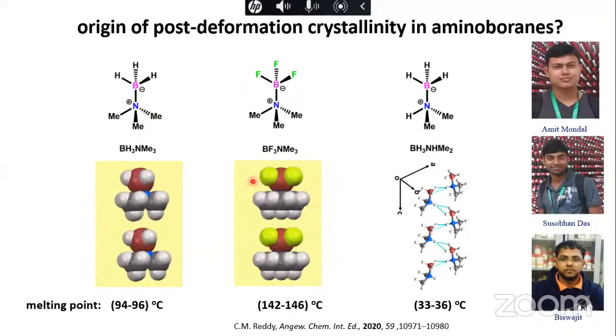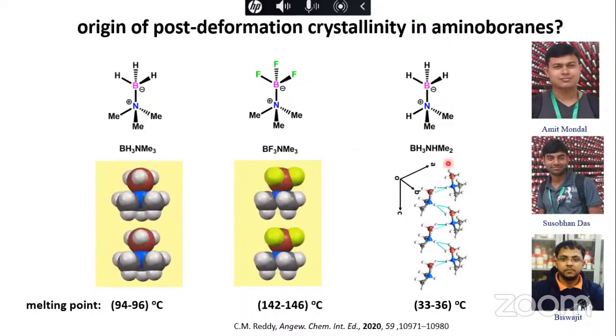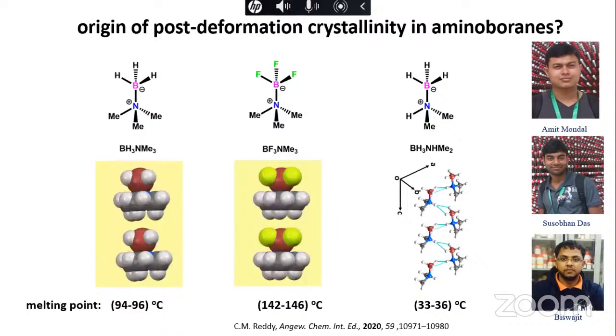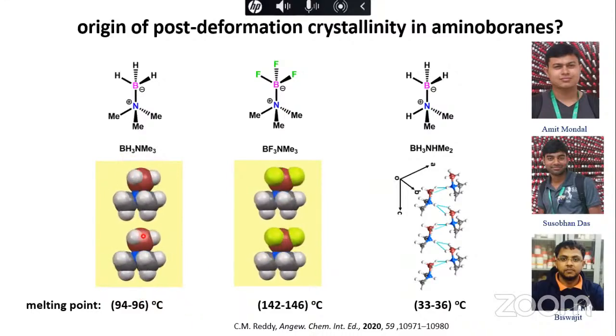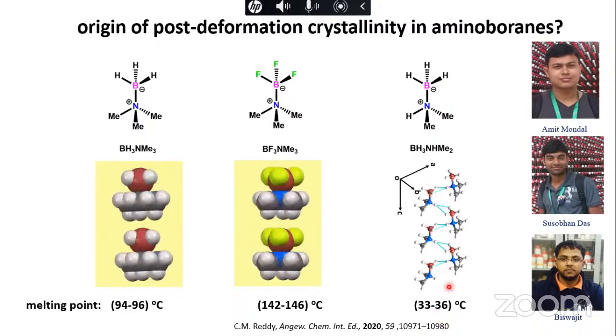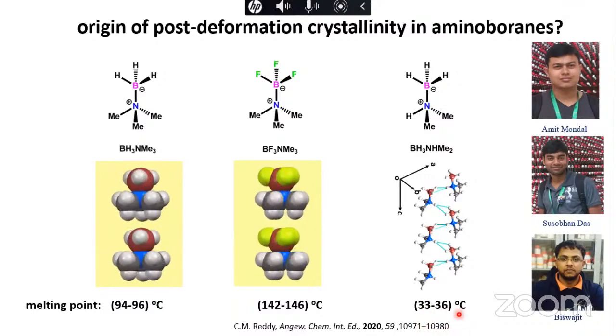And that is why these form these dynamic crystals where you have rotational degrees of freedom, or you can also call them plastic crystals, but this one does not form a plastic crystalline state. If you look here, the melting point of this is 94, and here it is 142 to 146, but here it is only 33 to 36 degrees centigrade. So here you are giving energy to the system, and they don't go into the melt, although they absorb a lot of energy. Simply they start rotating, but still it maintains the crystallinity. But here, once you give some energy, no rotational degrees of freedom are activated. So if you just heat it up to 36 degrees centigrade, these crystals simply melt. So that is the difference.